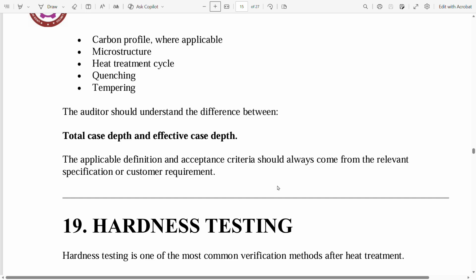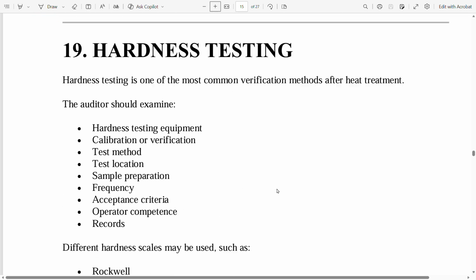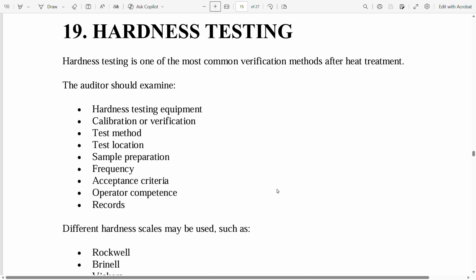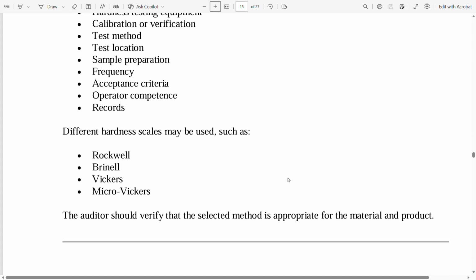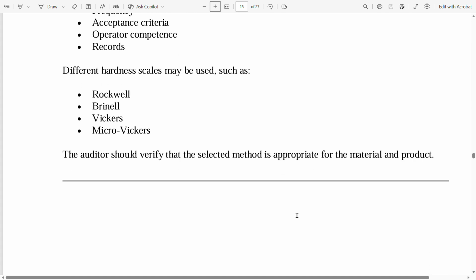Then 19th, hardness testing. Hardness testing is one of the most common verification methods after heat treatment. The auditor should examine hardness testing equipment, calibration or verification, test method, test location, sample preparation, frequency, acceptance criteria, operator competence, records. Different hardness scales may be used such as Rockwell, Brinell, Vickers, Micro Vickers. The auditor should verify that the selected method is appropriate for the material and product.